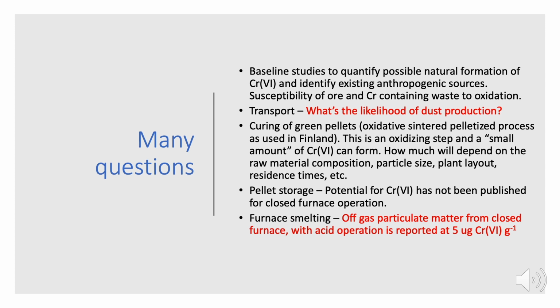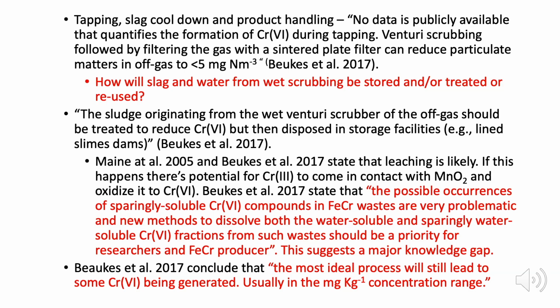Furnace smelting, the off-gas particulate matter from closed furnace with acid operation is reported at 5 micrograms of chromium-6 per gram. Tapping, slag cool down, and product handling. No data is publicly available that quantifies the formation of chromium-6 during tapping. Venturi scrubbing followed by filtering the gas with a sintered plate filter can reduce particulate matters in the off gas to less than 5 milligrams per meter cube.